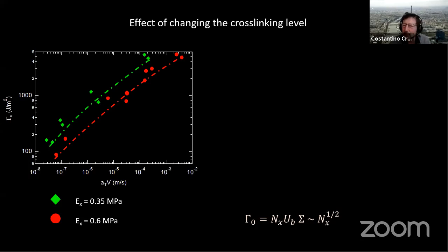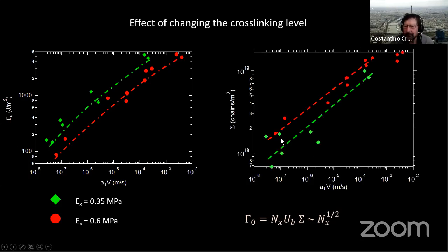Now, how about breaking bonds? If we look at bond breakage in the material, do we see an effect? And the answer is, of course, it's very noisy, but it looks more like our less cross-linked material breaks fewer bonds. And also, here a parallel line, we can argue. I mean, we definitely need probably more data, but it looks like this effect is really true over the whole range of velocity. So it's not just the threshold. So it means that somehow the less cross-linking also affects viscoelastic dissipation. It doesn't only affect threshold condition.